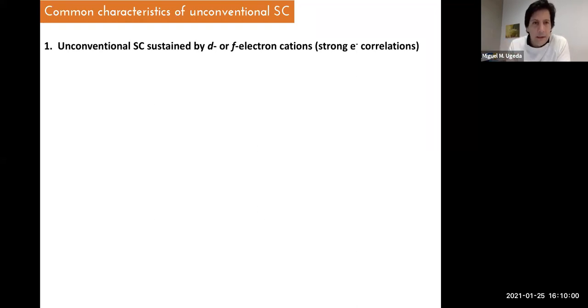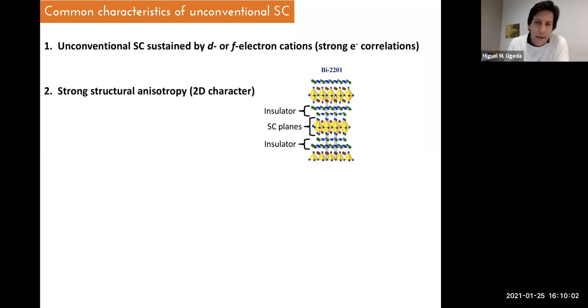Another common characteristic of this unconventional superconductivity is their two-dimensional character. So in general, their atomic structure shows a strong anisotropy. Here I show you an example. This is a cuprate superconductor, where you can see that the superconducting planes are basically confined in two dimensions or nearly two dimensions, few atomic planes, isolated by other planes. However, the material in general, I mean its bulk, is a three-dimensional material.